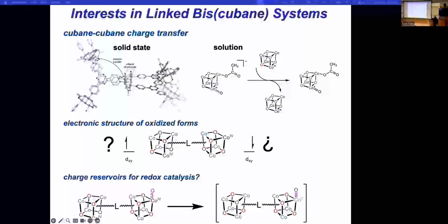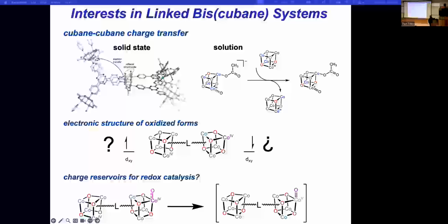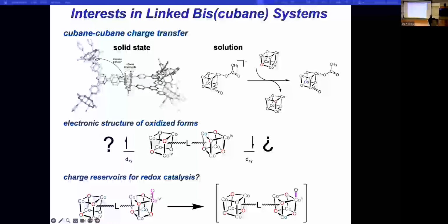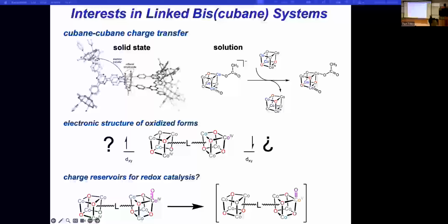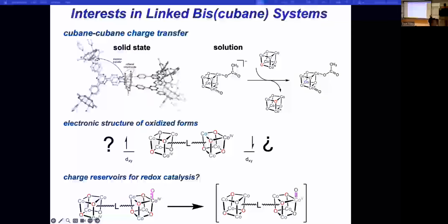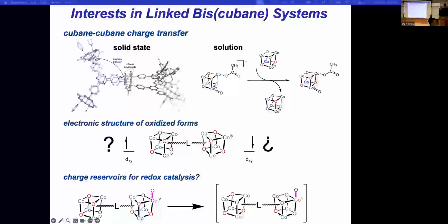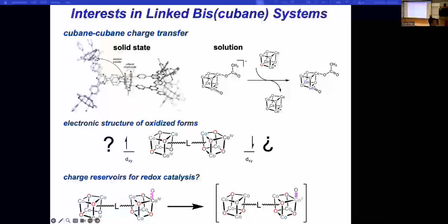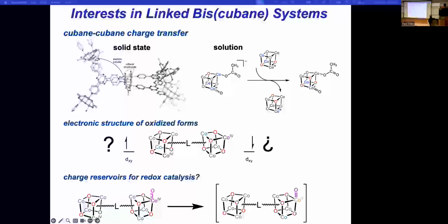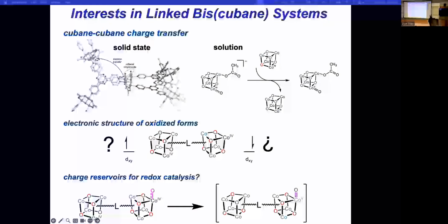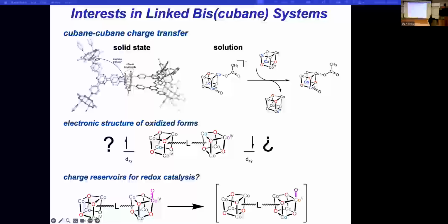Okay, the final topic I want to hit on has to do, again, with electron transfers between cubes and the whole question of how holes move around in these little fragments of oxide. Now, this is interesting in a couple of contexts that I've already mentioned. One is that in the MOF-type material that I showed you, there's good indication that there's redox disproportionation there. But certainly, we're seeing it from kinetic data in solution.